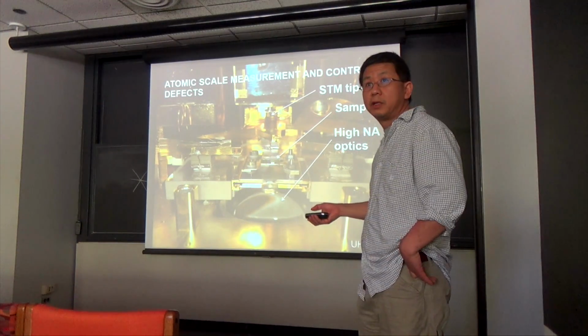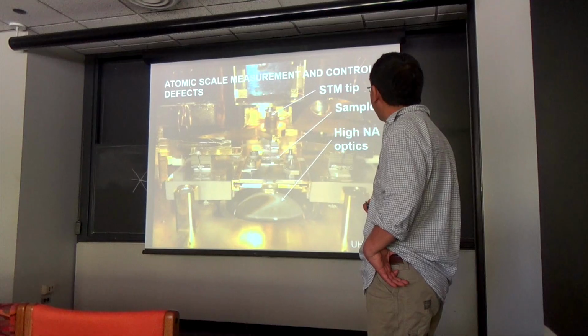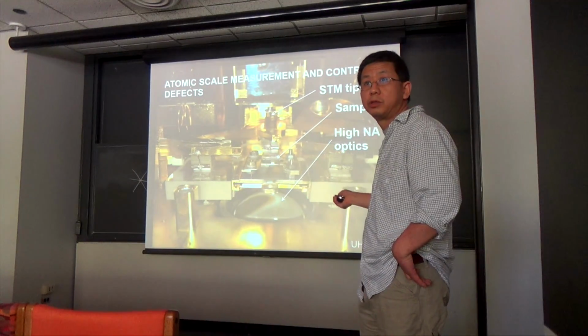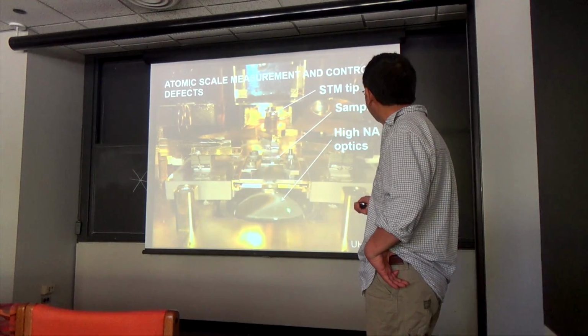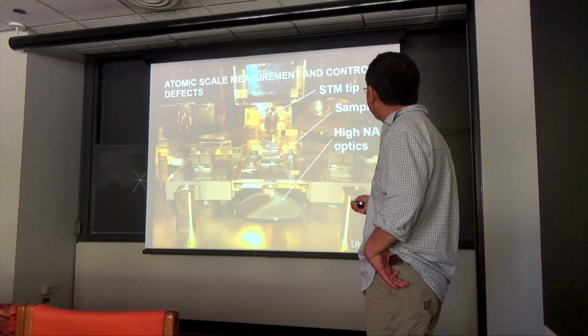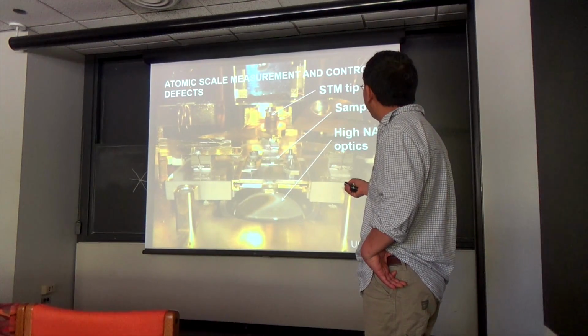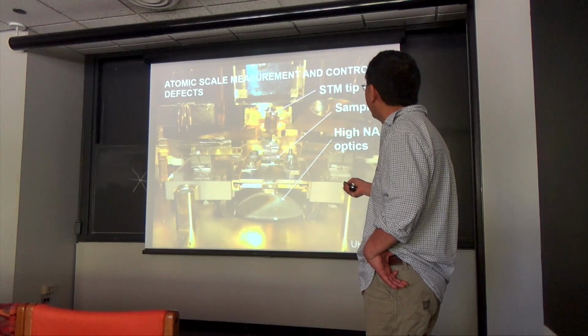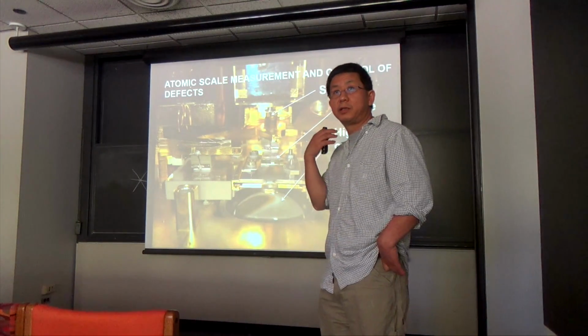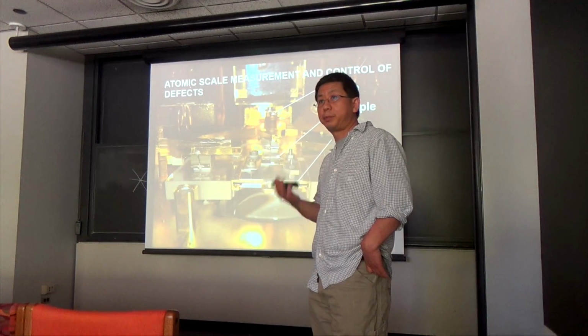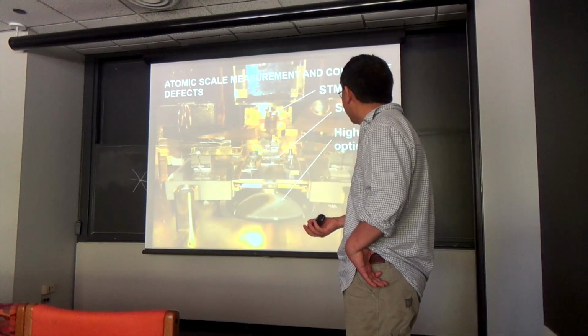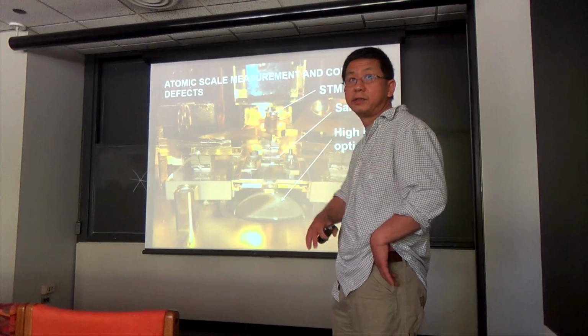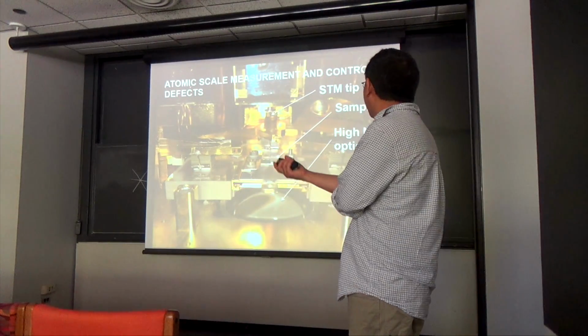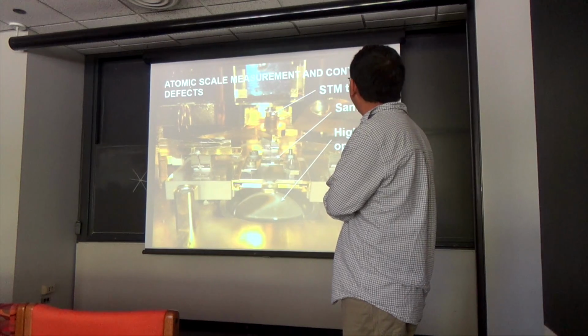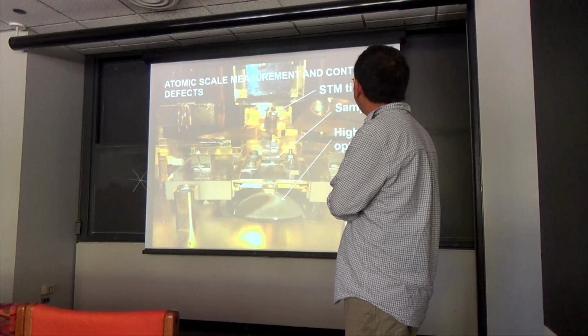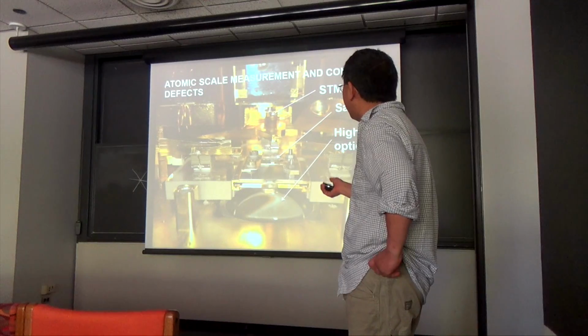The unique aspect of the system is that it combines optical excitations with a scanning probe. This is a high numerical aperture optic, and this is where you put the sample. The STM tip is coming from the top. Essentially, what they want to do is excite the sample with light into high excited states, and then probe these samples' electronic states by STM. These are things that they built themselves.